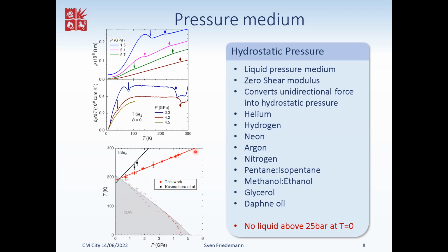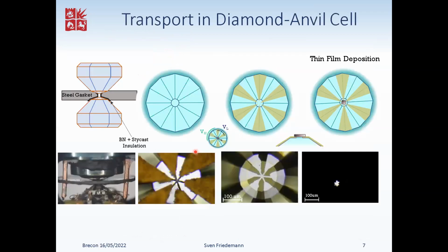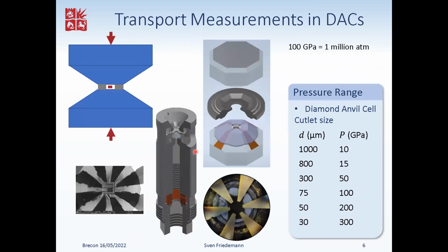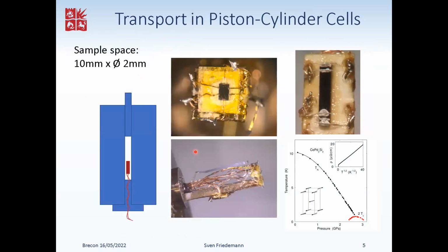Okay, measuring the pressure. Actually, I don't have a slide for this, but I want to answer Jörg's question. There are different ways to do this. One way is indicated here. I've got a strip of lead inside a piston cylinder cell, contacted for resistance measurement, and one can simply trace the superconducting transition of the lead, which is known in how it responds to pressure. In fact, that relates via thermodynamics to the volume change at the transition temperature. So that's quite well known and understood, and one can use this as a pressure gauge.